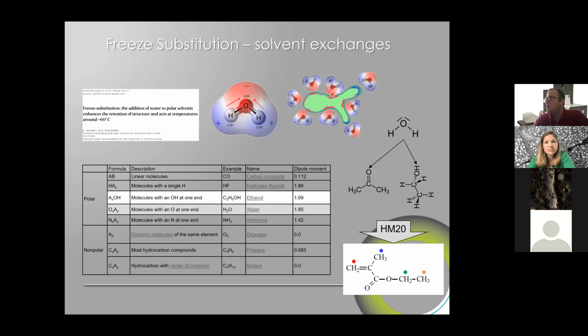substitution. And so then we go from the water molecules, which is rather thin, to a solvent. Here is the acetone and here is the ethanol. We see that the structure is quite different. The acetone in the end has 3 carbons, so it's a bit bigger than the ethanol, but then it has the same type of polarity as water has. So it's a very polar molecule compared to ethanol, which is slightly less polar. And then we replace that by HM20, and this is one of the key questions we have here. And basically we try to embed the sample into a resin.